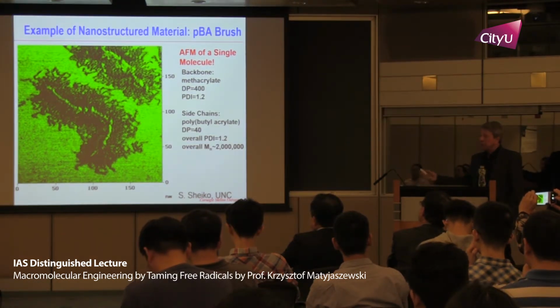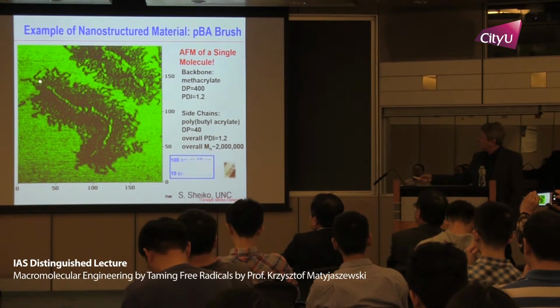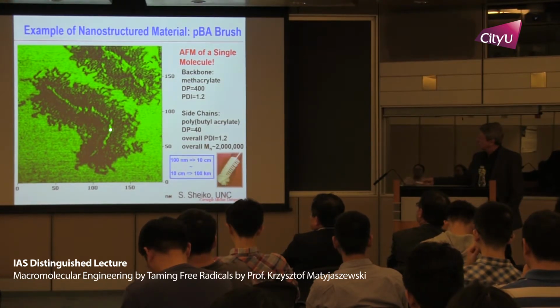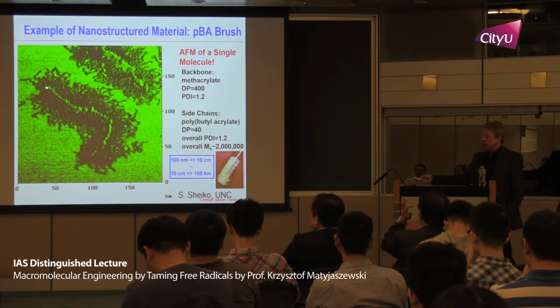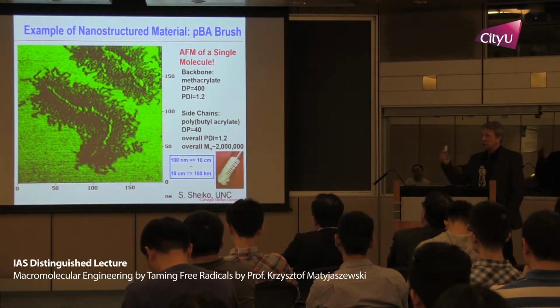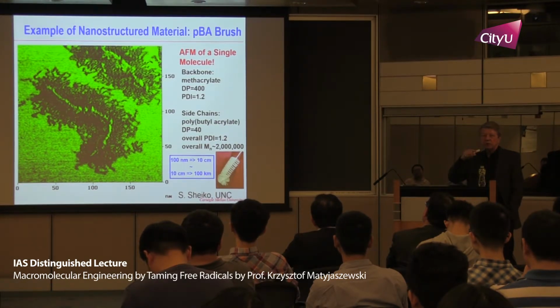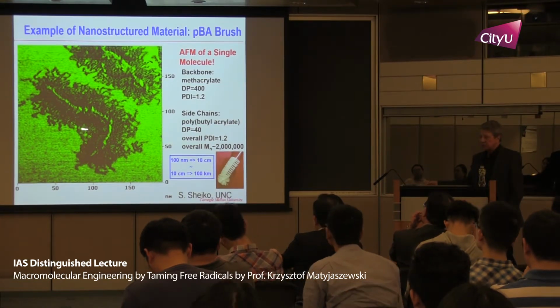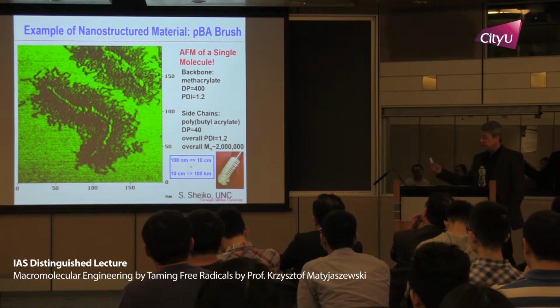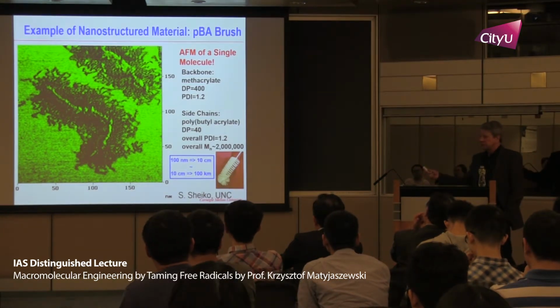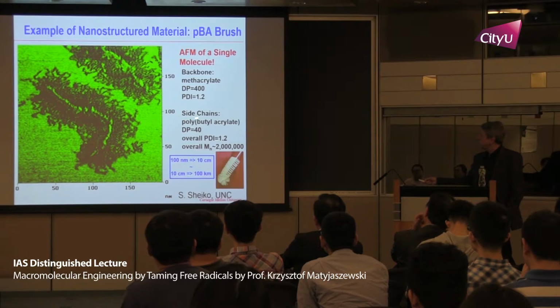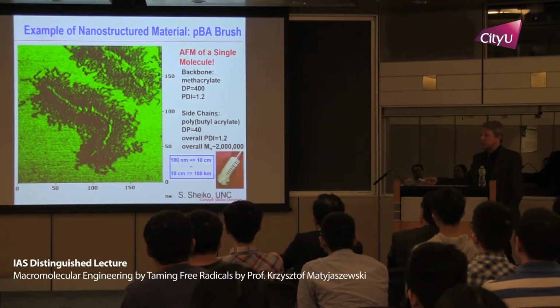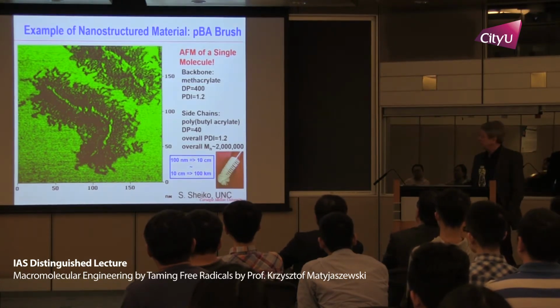So here's an example of a molecular brush. We make them first by constructing a backbone, degree of polymerization 400. We start with hydroxyethyl methacrylate, the same HEMA, polyHEMA, which is used in contact lenses. Then we convert every hydroxy group to a bromoester, and then grow these side chains. So this is a very special material because it's very soft. It's based on polybutyl acrylate. 95% of the material is polybutyl acrylate.